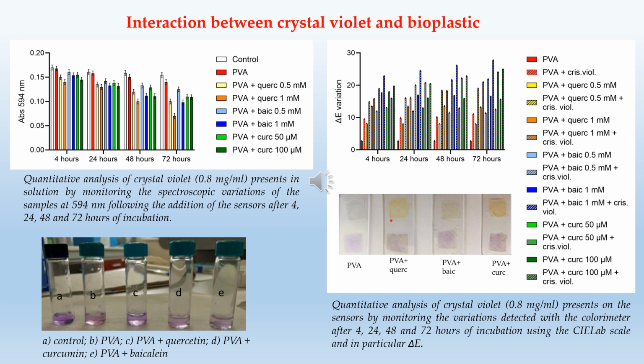After just 4 hours of incubation, a decrease in the absorbance values of the solution recorded at 594 nanometers was noted, in particular for the quercetin, which increased with the passage of time, up to 72 hours. This color shift of the sensors towards violet was quantitatively analyzed. In fact, the graph shows the transfer of the organic pollutants onto the bioplastics and, in particular, the greater effectiveness as an adsorbent if the polyphenols are linked to the PVA.